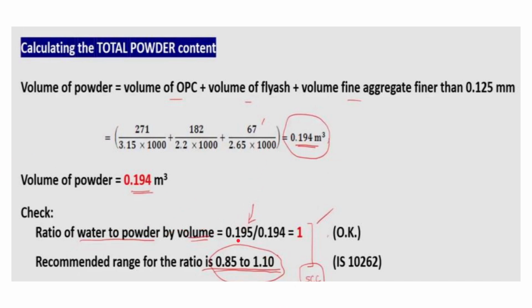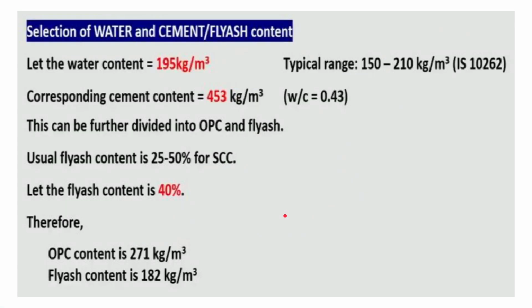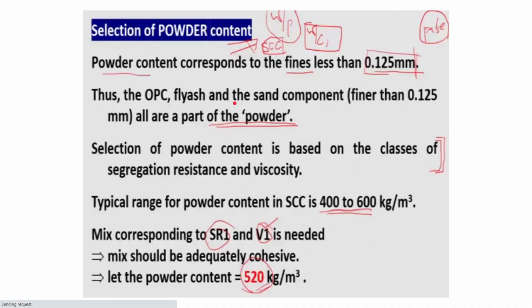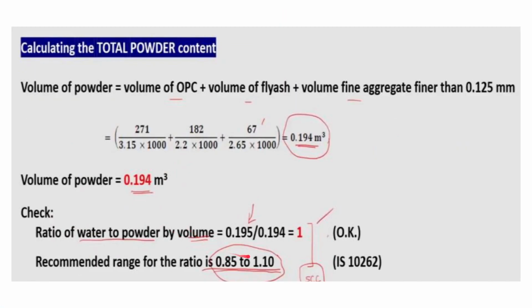Water, we assume to be 195 kg per meter cube. So the ratio of water to powder by volume will be 0.195 by 0.194. The value will be around 1, slightly more than 1, but about 1. The recommended range for the ratio is 0.85 to 1.10, and because 1 is between them, as per IS 10262 the value is okay.